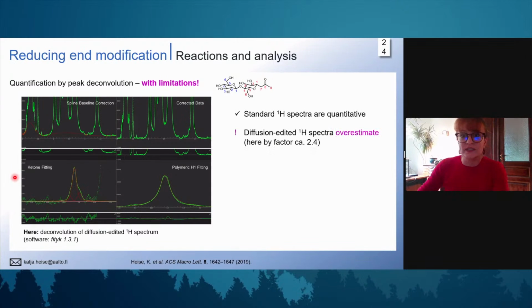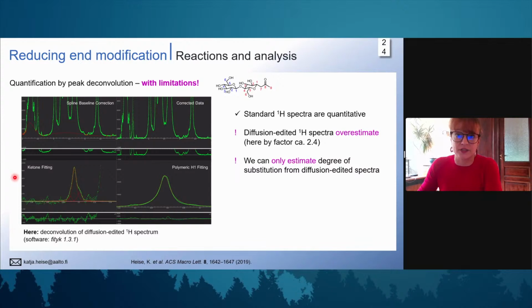However, we lose this quantitative information for our diffusion edited spectra because of the faster relaxation of the cellulose backbone, because it's very stiff compared to the ketone functionality we attach later or any other substituent. We overestimate the signals of our new substituent, so of our ketone functionality, by a factor of 2.4. So it means we lose quantitative information. What we can still do is that we estimate the degree of substitution.